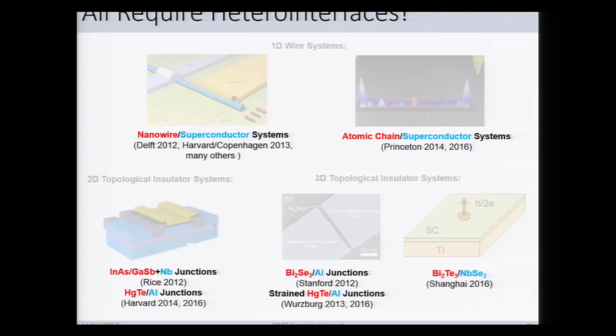Okay? So we have, say, the nanowire, where you have to get rid of this oxide layer or avoid it, that would occur on the semiconductor nanowire, and then deposit a superconductor. Ideally, your superconductor will be epitaxial, so you can have as clean of an interface as you can. This has been pretty much achieved, and there's a lot of excellent results happening there. And there are many other materials interface platforms that are being used to try and access this sort of physics.